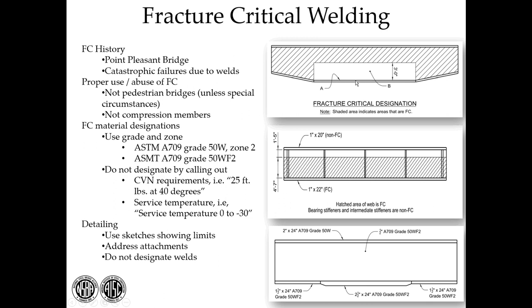When you look at this web, you may think, well, the fabricator is probably going to just use one plate, so why does the fabricator care? Well, the weld up here is going to be fracture critical, but not necessarily down here. And also, if there's a weld going across the plate, down here it wouldn't need to be a fracture critical procedure. Now, if a fabricator was welding across that area, the fabricator would use the same procedure, just logically. But if there were a repair or something else that was an issue in the material in this area where we're not fracture critical, then the requirements are different. So you really need key details on what is and what is not fracture critical.